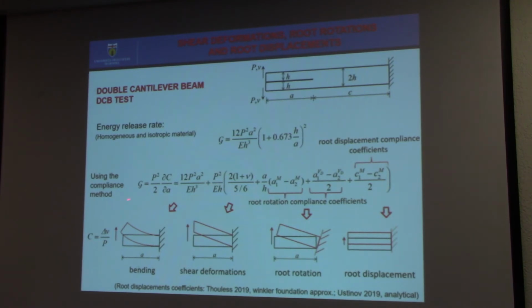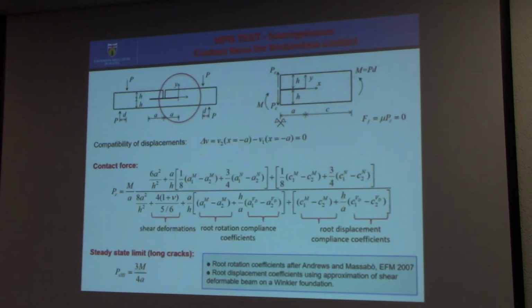If we use this method, these coefficients cannot be found in the literature, so what we did to calculate the root displacement was to assume that this material here can be treated as a shear deformable beam on a Winkler foundation. And by doing that, we were able to obtain this compliance coefficient. So we decided to apply this approach to our inverted 4-point bending test.